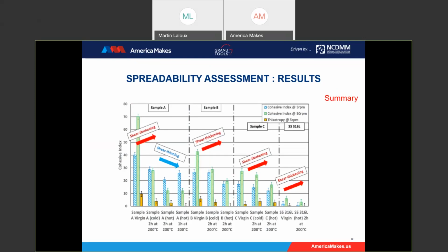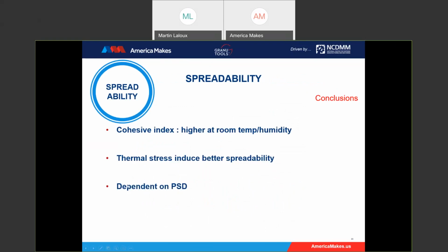Regarding the process powders, especially for samples A and B, the thermal stress completely changed the behavior, with a modification from shear thinning to shear thickening. Globally, every powder achieved a better spreadability, so a lower cohesive index, when it was heated up and after cooling down. However, sample C and stainless steel are not highly affected. So the conclusion on the spreadability: the cohesive index is higher at room temperature and humidity. The thermal stress induces a better spreadability, and it's really dependent on the PSD.